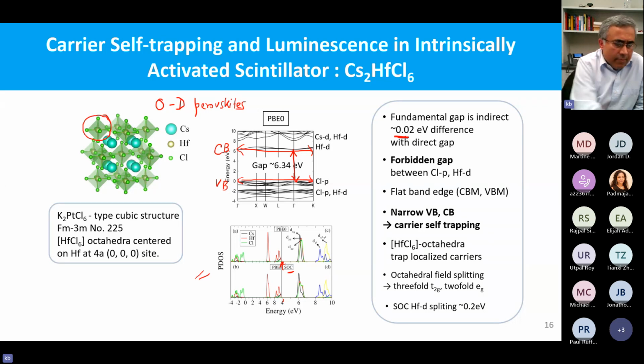The other is the bottom of the conduction band, which is right there, made up of hafnium D states. Now, if you dig a little bit deeper, you will see those hafnium D states are actually split into these D states, what we call the T2G levels, and these are the EG levels. This comes from symmetry considerations. Of the D levels, you have three degenerate T2G levels right there, and two degenerate EG levels.